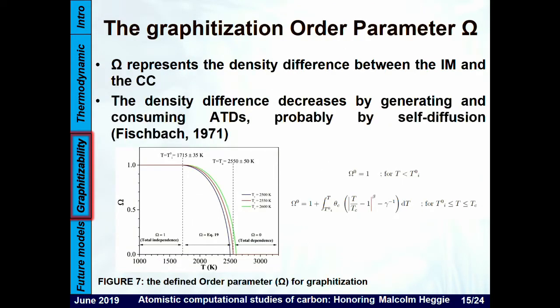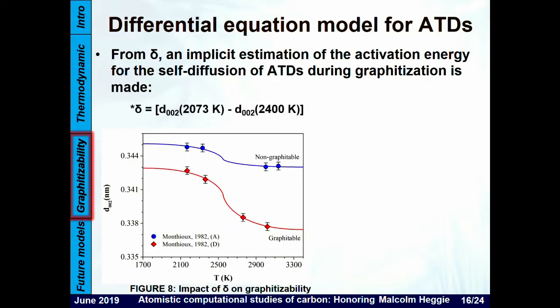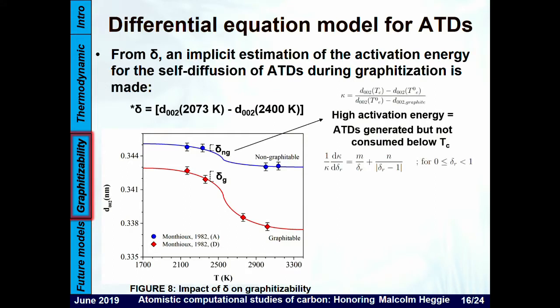After that, the challenge is to make a mathematical approach to represent this mechanism. Fortunately, we can use thermodynamics because the local equilibrium hypothesis is assumed to be general, to be acceptable. If we do that, we can use an order parameter and some differential equation related to the change of D002 in the critical region between 1700 Kelvin and 2550 Kelvin to essentially implicitly integrate in the model the average activation energy for the annealing of the ATDs during graphitization.